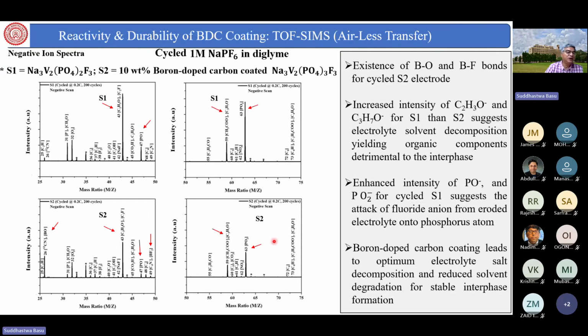Now we are showing you the negative ion spectra. We were showing you positive ion spectra. You can see a lot of increase. This is 200 cycles, and all these are 200 cycles, between S1 and S2. And you can see that the organic structure after 200 cycles has increased enormously for S1, and for S2 there is not much increase, a slight increase but not much. So it shows that when we had a BDC coating, organic CEI is not forming or forming less compared to S1. S1 did not have a BDC coating, so it is forming a lot of organic CEI, which gets degraded over time. That's the reason why we do not want organic CEI, but we want inorganic CEI.